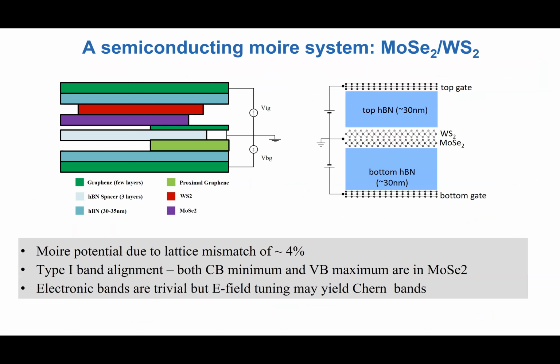So all you just showed was for putting electrons up in the orbit. And I don't know about the material, but is it kind of an S character? Is it like an S symmetric for the electrons and P symmetric for the holes? No, it's not like that. So actually the orbitals are predominantly d orbitals of the transition metal. So the conduction band is something like 90-95% d_z² orbital, and the valence band is d_xy plus or minus i d_x²−y² orbital. They do hybridize with the chalcogen p orbitals, but I still find it very surprising that at the K and K prime valley, this hybridization is relatively weak. So like 10% for valence band, 5% for conduction band.